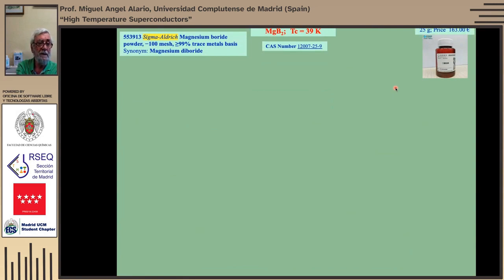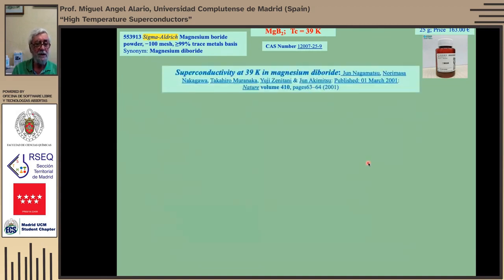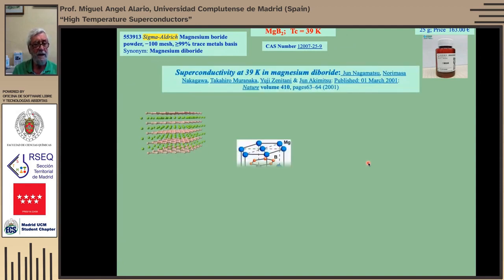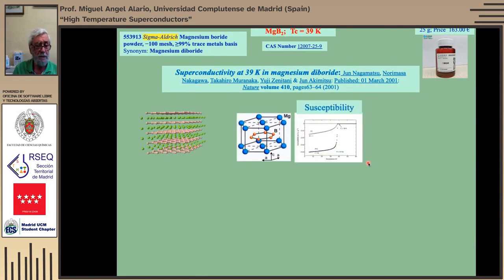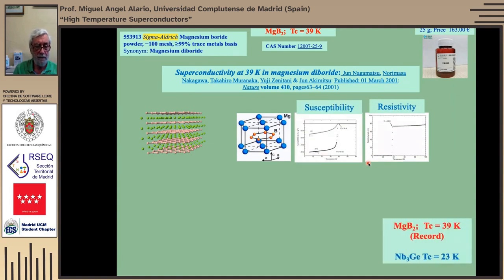Of these materials, magnesium boride was just bought. It was rather expensive, but it was a superconductor. Nobody expected that, and Akimitsu in Japan just decided one day, for reasons that are not clear, to measure the properties of this thing from the store, and it's really a superconductor, also at rather high temperatures. Which was really the record for materials that are not cuprates. And you have this one, which is also an interesting one, but at a much lower temperature.